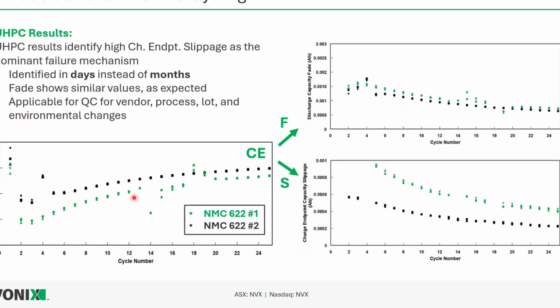If we look at the UHPC results, you can see that just in about 20 cycles, but we can tell within about 10, which is only about a week of cycling, that this batch number two has very, very different Coulombic efficiency. It's a lot higher. Obviously, these cells are cycling a lot better somehow. But we didn't see that in the capacity fade. We didn't see that early in cycling.